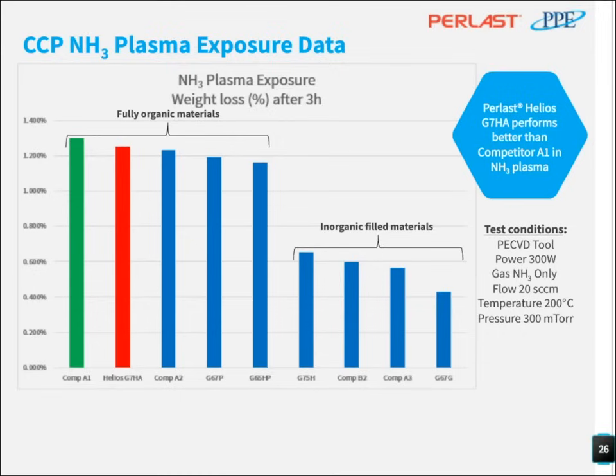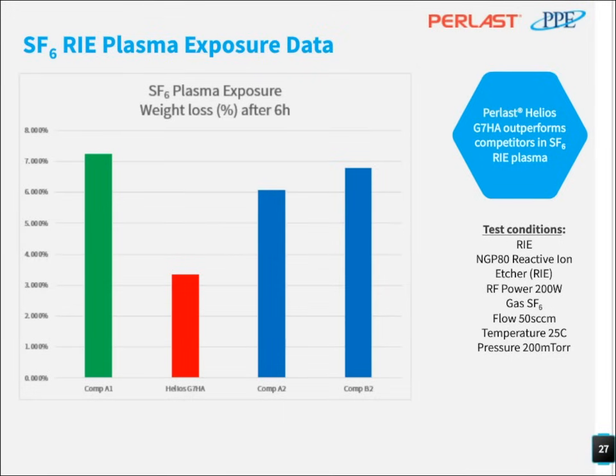inorganically filled materials perform significantly better than fully organic materials in ammonia plasma. So if you need a highly ammonia plasma resistant material, then we'd recommend you use, for example, G67G or other inorganically filled materials. But this material also has quite a low etch rate in comparison to the competitor material. So let's move to another chemistry. You can see another fluorine chemistry, SF6. Again, Perlast Helios material performs very well in SF6 plasma as well.